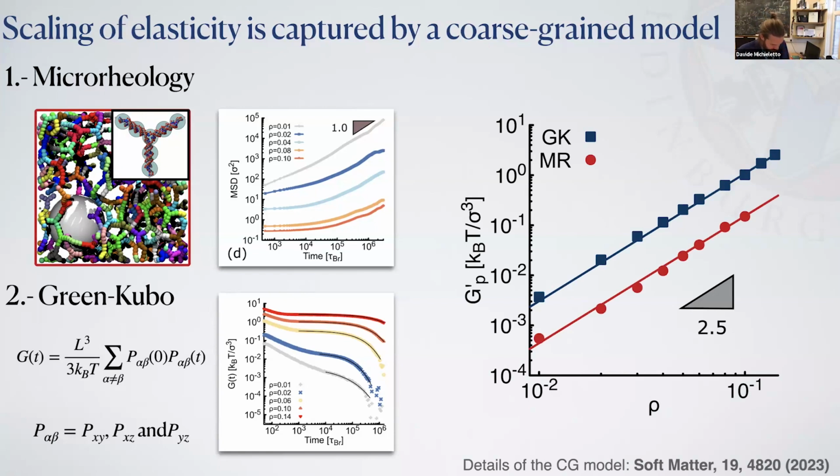Now, the fact that we get the same exponent tells me 2 things. Essentially, we didn't change any parameter here. We just got 2.5 straight off the simulations. So it was quite impressive. And so this gave us, one, confidence that the simulations were quite representative of this experimental system, and 2, that the exponent was right in some sense, because we got it from 2 microscopically different systems, but somehow macroscopically similar, so the scaling is the same.